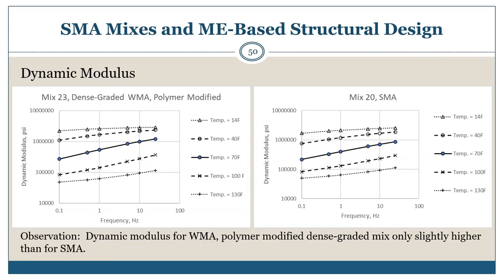The properties measured in the laboratory have shown that the dynamic modulus for warm mix asphalt, polymer modified dense graded mix is only slightly higher than for SMA at different test temperatures, as shown between the two graphs on this slide. The graph on the left, mix 23, is for dense graded warm mix asphalt, but with a polymer modified asphalt. The graph or figure on the right, mix 20, is for an SMA mixture. The observation: dynamic modulus for warm mix asphalt, polymer modified dense graded mix is only slightly higher than for the SMA mix.